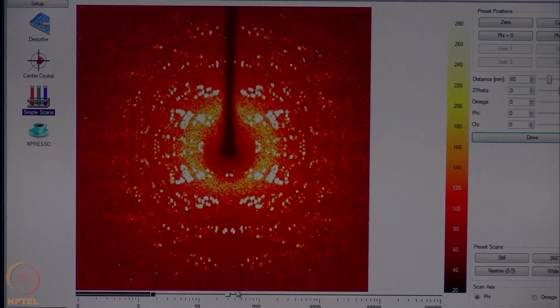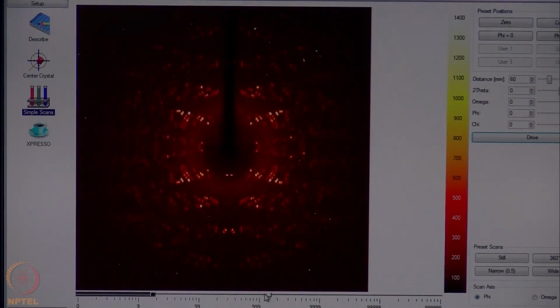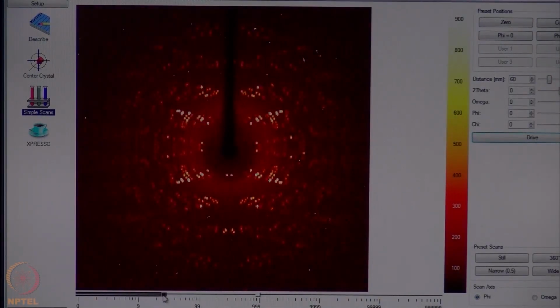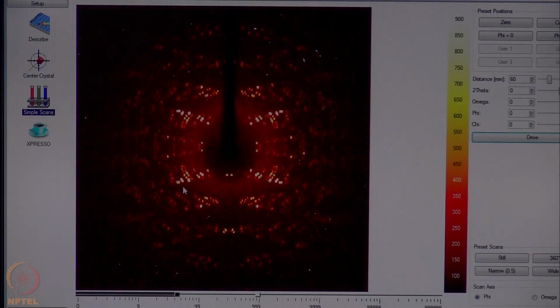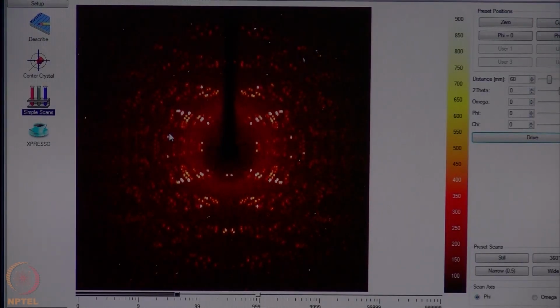So this is the rotation photograph which we have recorded by rotating the crystal about phi by 360 degrees in about 1 minute. So what you can see are the diffraction spots, and those are centrosymmetric in nature. If you remember the class, I have shown you a rotation photograph. Of course, that rotation photograph was on a crystal of sodium chloride which has a very high symmetry, and that is why the spots were highly symmetric and distinct. Here it may be a monoclinic or triclinic lattice which has a very low symmetry and a large number of spots, and many spots are getting merged in this window.